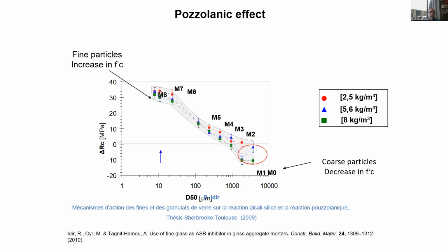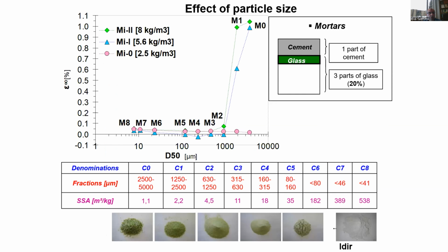Of course, because of the reactivity of this material, don't use it when it's very coarse, unless you use special mitigation, because when it's coarse, it will create cracks, because you have ASR, which can form here. So the finer the material, the higher the reactivity, then you can gain a lot. But when you go to the expansion, if it's very fine, as you can see here, then you have mainly the CSH formation.